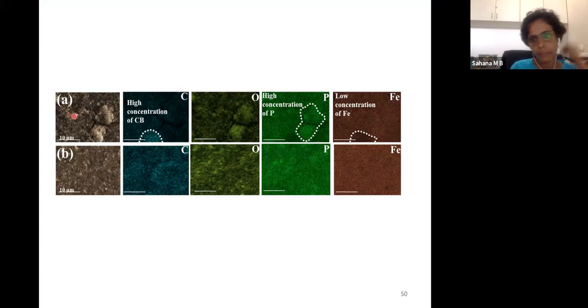The A corresponds to the one where carbon black and LiFePO4, which is the active material, are sequentially added to the liquid solvent. Whereas in this case, carbon black and LiFePO4 are pre-mixed and then they are added to the PVDF NMP. We don't see any segregation here.